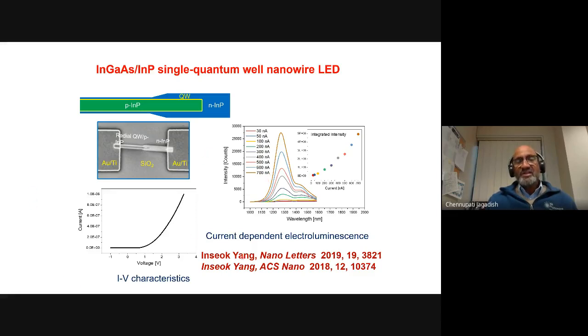You can see the IV characteristics is showing diode-like behavior, indicating that he's able to be successful in making ohmic contacts. So now we are injecting the current and looking at the light coming out of these. You can see the higher the amount of current you're injecting, the higher the amount of light coming out. You see two emission peaks at 1.3 and 1.55 microns.